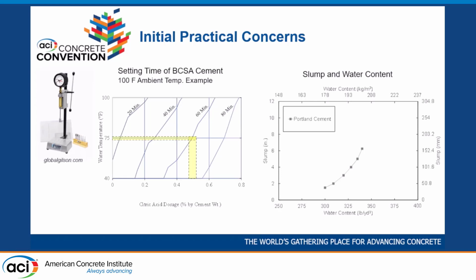Another practical concern is slump. We need an adequate slump if we're going to place concrete for a structural element. It's got to form around the rebar and all of that. So for Portland cement, for a 1-inch nominal maximum size aggregate, we have a curve like this. This tells us if I use 325 pounds of water, I should get a 3-inch slump. This is like the first step of mix design.